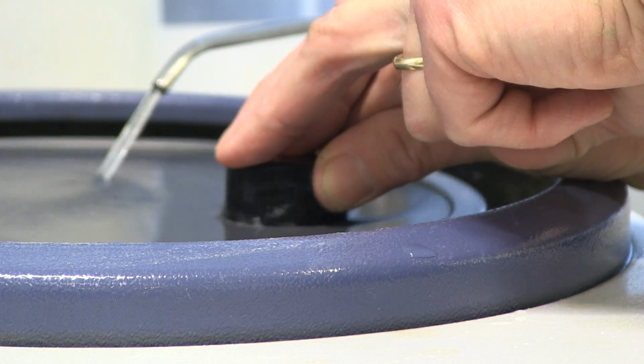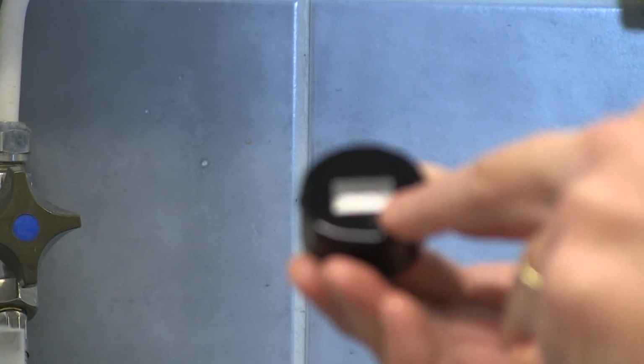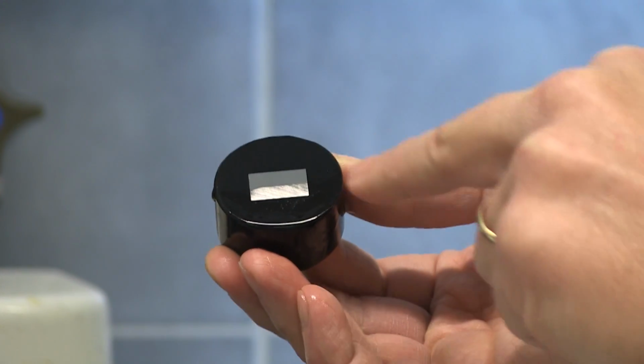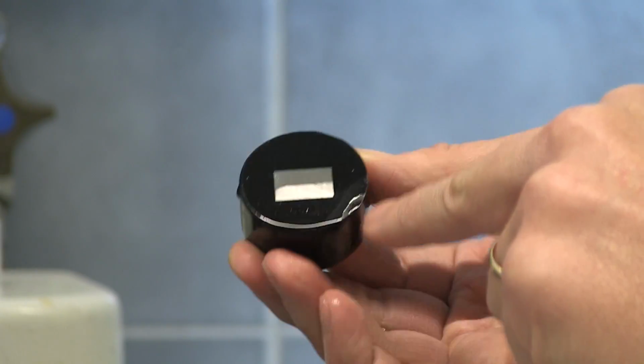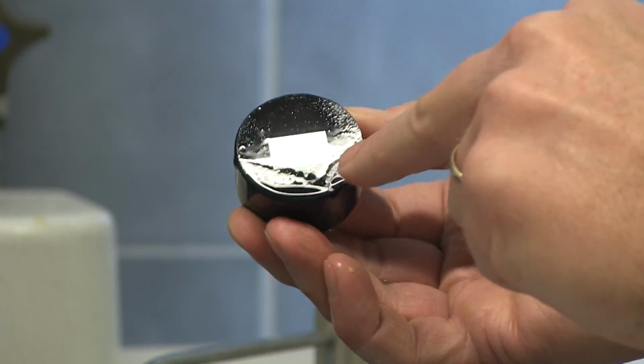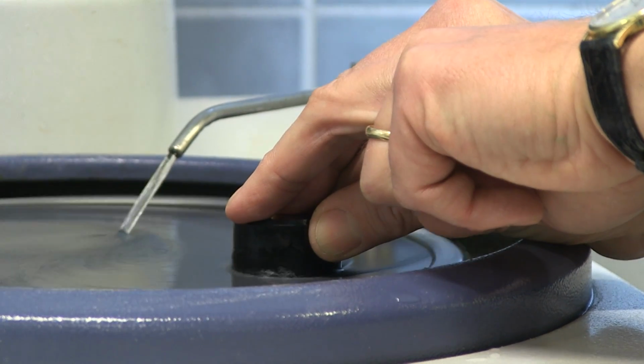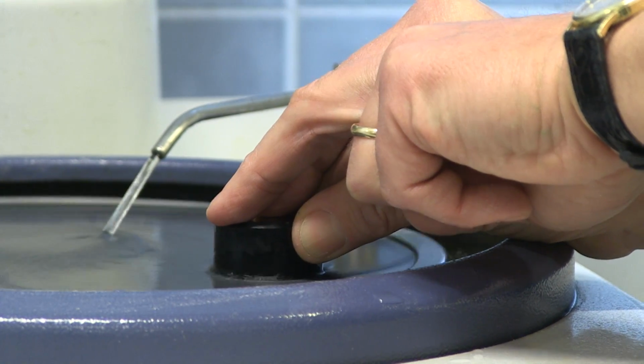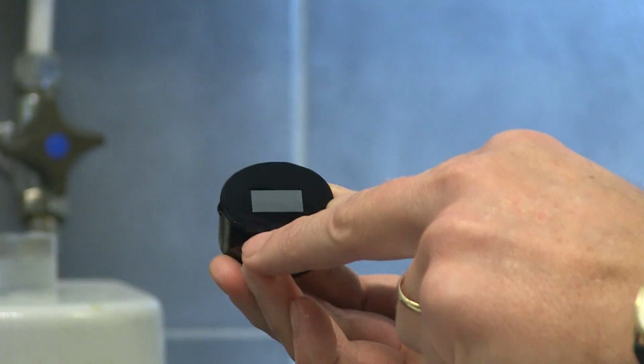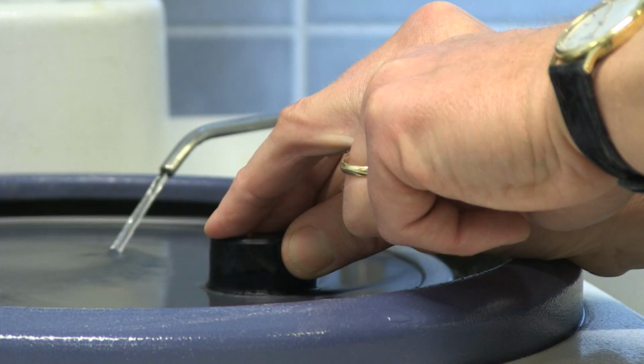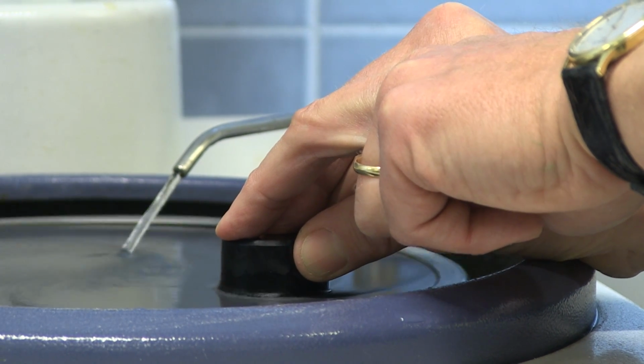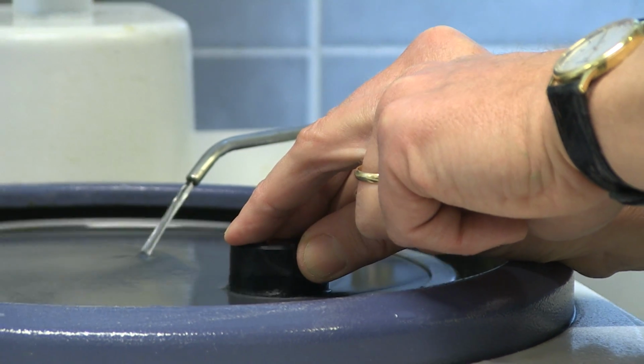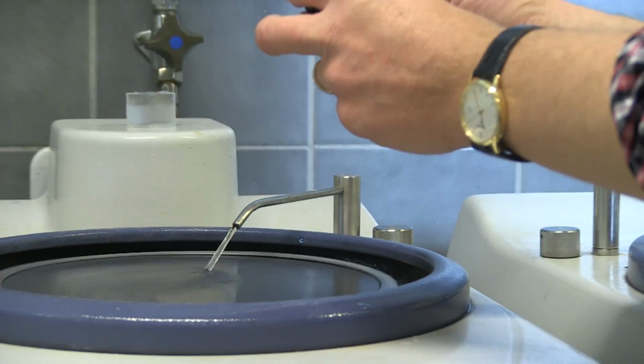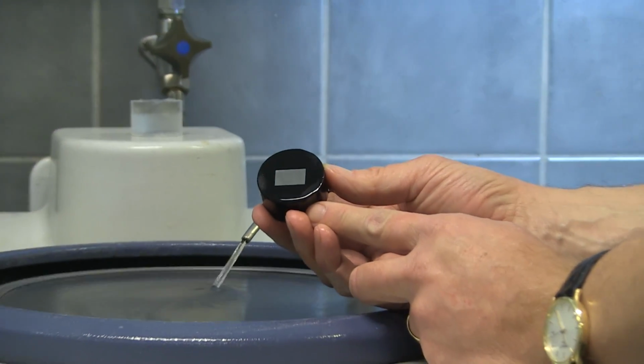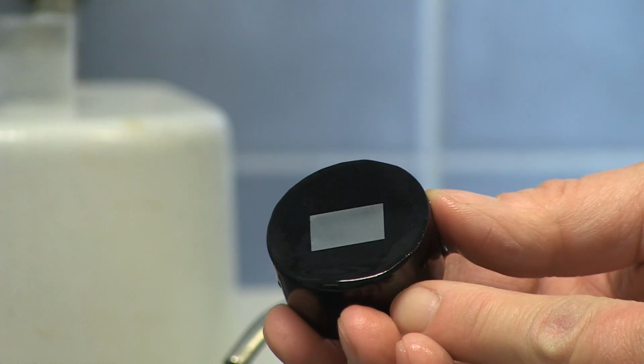And after a few seconds I check, and I can see that I'm grinding, but I haven't been grinding the whole surface, so I haven't been holding it flat. So next time I put it down, I put a little bit more pressure on, in this case, the back side of the sample from your view. Check again. Yes, I'm going in the right direction. And a little bit more. And now the whole surface is ground. Maybe it's difficult to see, but now I have scratches in that direction.